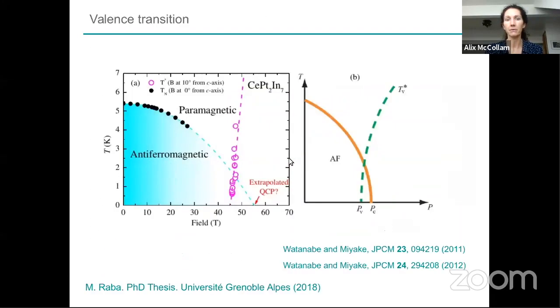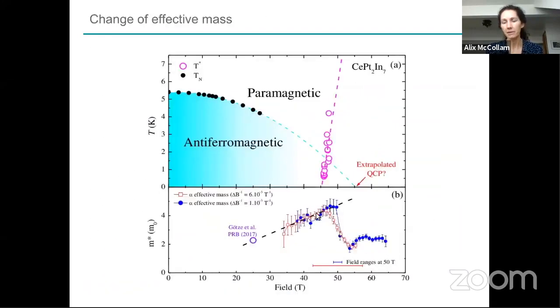So here I show that the mass does change a little bit. This is done over an overlapping field region between about 35 and 60 Tesla. And we do see a slight change in this alpha mass, but that's as much as we can say about changes in the Fermi surface at high field. If there was a big change in the Fermi surface, we would see it because the resolution is rather good for these oscillations, I think.